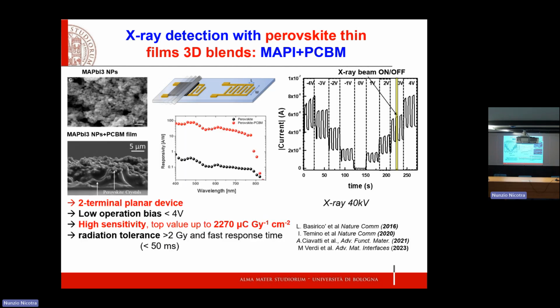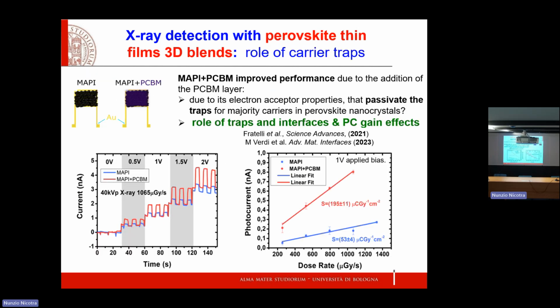And this is the response to X-ray. You clearly see the X-ray beam on and off for different biases applied, positive and negative. You see the nice reproducibility for each bias, and of course the increasing delta I in collected current produced by increasing bias. What is nice to see here is that the response of pure MAPI and MAPI with the blend is very different. The red curve is related to the blended material, meaning that the one with the blend has a much better performance. Why is it so?